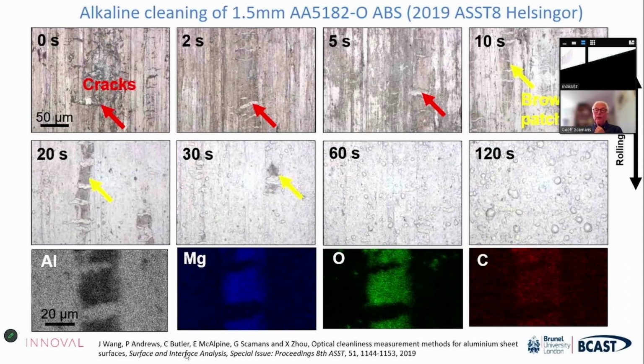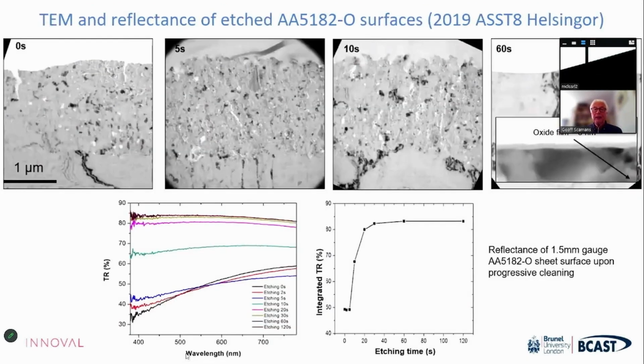And it just really shows that if you understand these surfaces and you understand that they have important optical properties, you can actually see whether they're there. So we can now monitor these surfaces and monitor cleaning, and we can actually tell whether cleaning and pre-treatment are successful by looking at the reflectance of surfaces or the colour of surfaces. And this is really quite important. And this is where we are now, and this is what we're talking about in ASST8 in Denmark in 2019, and we'll be talking about it again in Stockholm next month.